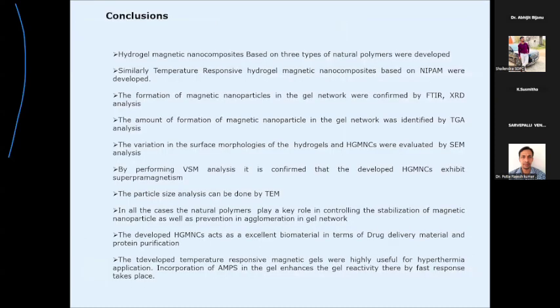So what are basically the conclusions? Hydrogel nanocomposites based on three types of natural polymers were developed. A temperature responsive magnetic hydrogel was developed. The formation of magnetic nanoparticles in the gel network was confirmed by FTIR and XRD analysis. The amount of magnetic nanoparticles formed in the gel network was also identified by TGA analysis.